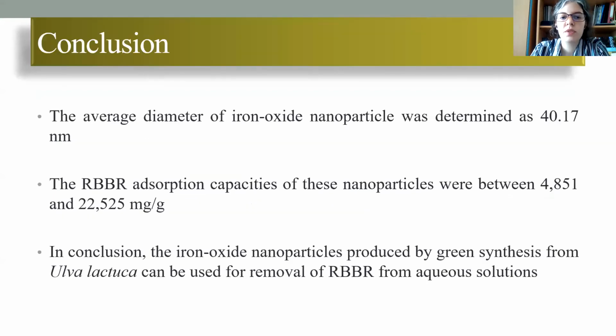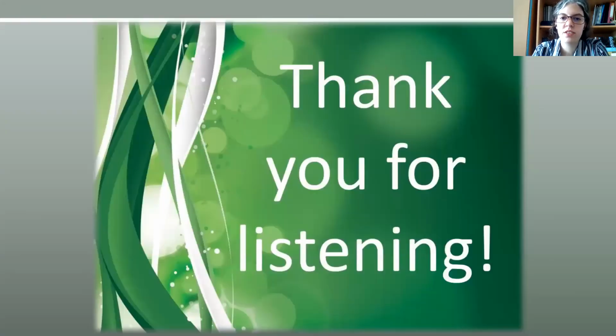In summary, we produced iron oxide nanoparticles of 40 nanometers, and the dye adsorption capacities of these nanoparticles were between 4 and 22 milligrams per gram. In conclusion, the iron oxide nanoparticles produced via green synthesis from Ulva lactuca can be used for removal of dye from aqueous solution. Thank you for listening.